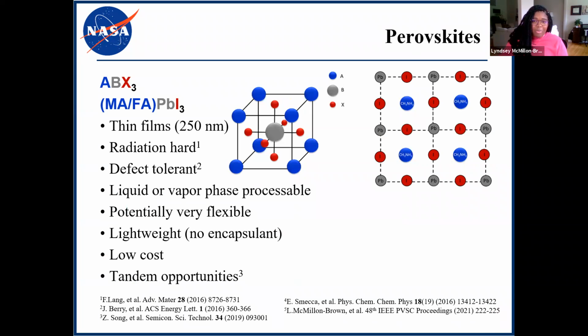The name perovskite applies to this structure of the material because the perovskites for photovoltaics take on the same structure as the perovskite mineral. Solar materials with perovskite structure are commonly hybrid organic-inorganic lead or tin halide based materials. The structure has a generic form ABX3, where A and B are cations and X is a halide. A popular mixture so far in the field consists of methyl ammonium iodide and formamidinium iodide mixed with lead iodide. But there are many different alloy potentials, and perovskites have a lot of favorable properties that make them enticing for space applications,